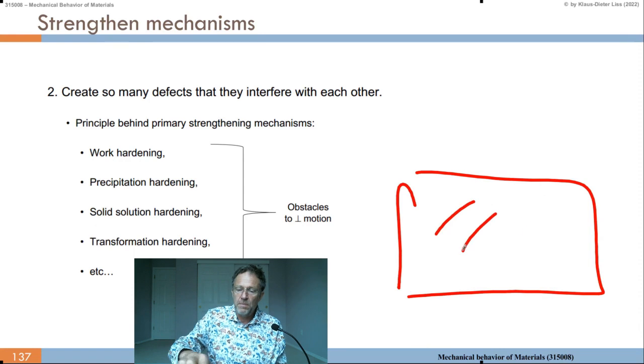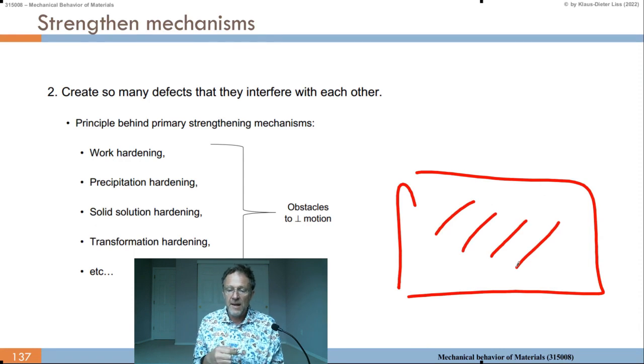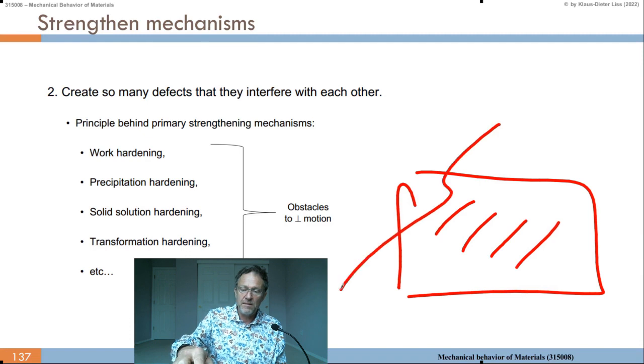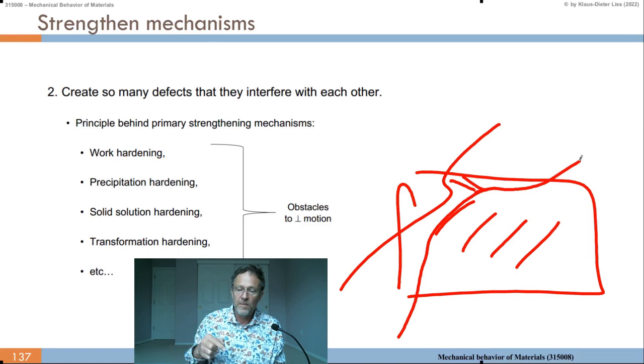We also can put precipitates into the crystal lattice. That means if we have a dislocation line coming through here and moving in this direction, it cannot move over the precipitate, or it needs a lot of energy to go over the precipitate. Sometimes it has to climb. We know climb at room temperature is difficult. It has somehow to go around.